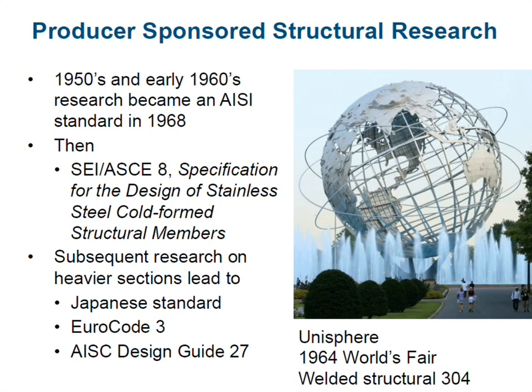There's a Japanese standard, Eurocode 3 has all structural sections, and the new AISC Design Guide 27 came out about 1.5 years ago. I was on the steering committee for that. All of this research was used first, not on the Arch, but the Unisphere can actually claim to be the first large structural application for stainless steel. The research was already in place. Of course, the Arch was under construction. But it was donated by the stainless steel industry as essentially a piece of advertising. It had stainless steel from every producer, 304 welded together, and is still doing well.